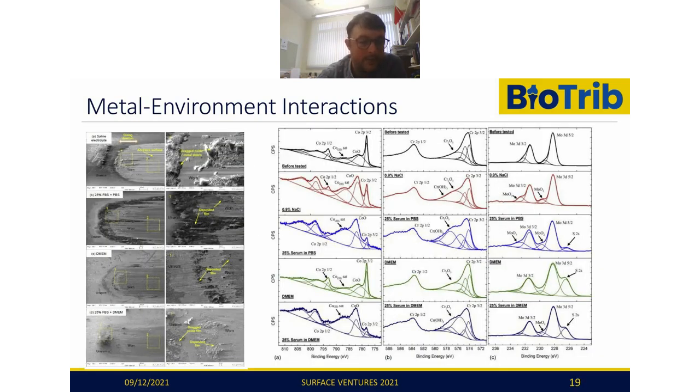And again, the tribochemistry of these becomes very complex. We see that the formation of these films is very different depending on the nature of the lubricants used. What was particularly interesting is there was quite a famous paper in this area that reported that low friction was induced by ordered carbon layers. We've not been able to reproduce that, but what we do see is that we get these complex moly-sulfur interactions. In areas where we tend to have high abrasion, we get a formation of moly oxides. But where we see low friction, we have the formation of these moly-sulfur interactions as well.